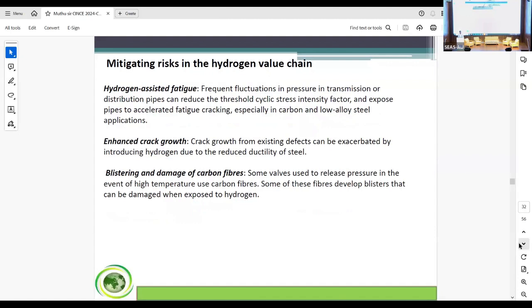And hydrogen-assisted fatigue: frequent fluctuation in pressure in transmission or distribution pipes can reduce the threshold cyclic stress intensity factor and expose pipes to accelerated fatigue cracking, especially in carbon and low-alloy steel applications. And enhance crack growth from existing defects. The crack growth can be exacerbated by introducing hydrogen due to reduced ductility of steel, blistering and damage of carbon fiber.